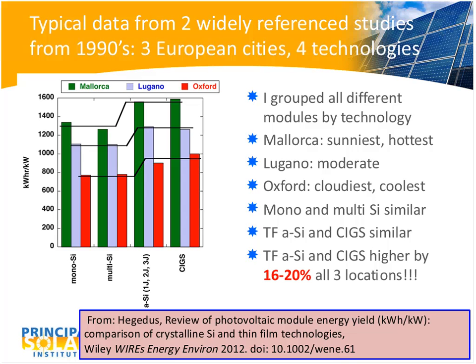But what you can see are very consistent trends as you go from the sites. The y-axis is the kilowatt hour per kilowatt that was reported. And as you go from Mallorca to Lugano to Oxford, from green to blue to red, you see a steady decrease in every technology in the output. Well, that's to be expected because of the yearly sun hours.